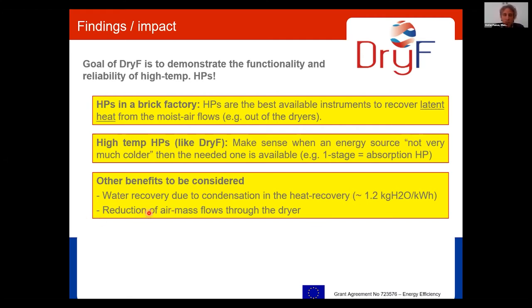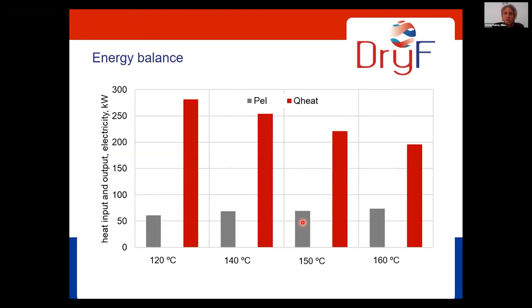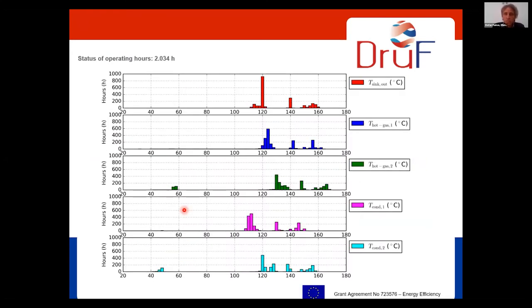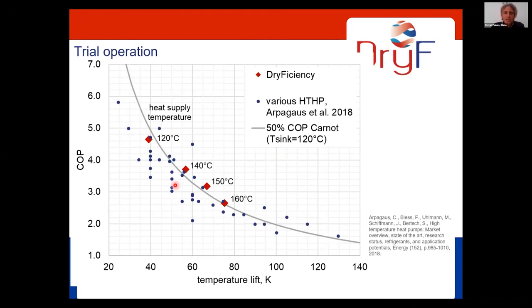And then the second benefit for the operation of our convection dryers is that we reduce the air mass flow through the dryer when we operate with internal heat exchangers. What have we seen so far in Uttendorf? We operated from 120 degrees sink temperature up to 160. You can make a calculation to find out the COP, but this was made by Veronika on another slide here.